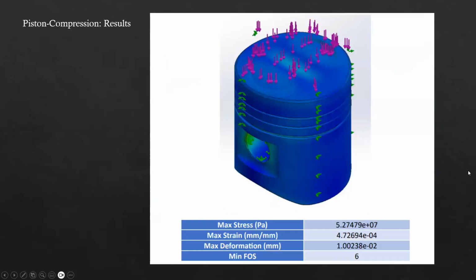The results are presented below. We ended up coming in with a minimum factor of safety of 6. Now, this is actually excessive, and we do recognize that the mass of the piston is significantly higher than a traditional configuration. Most of the examples we found online were somewhere in the neighborhood of 200 grams versus our 400 plus, which is what's leading to this high factor of safety. In an additional redesign, we would consider shaving additional material off the side of the skirts, but for simplification purposes, we decided to proceed with this model of the engine.